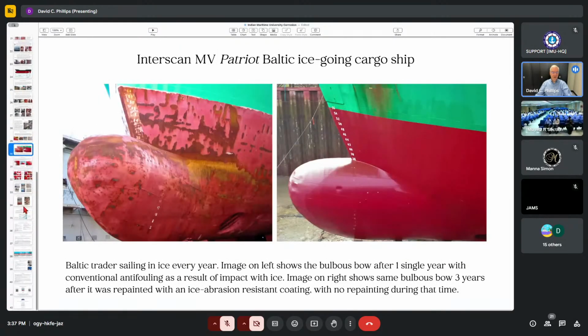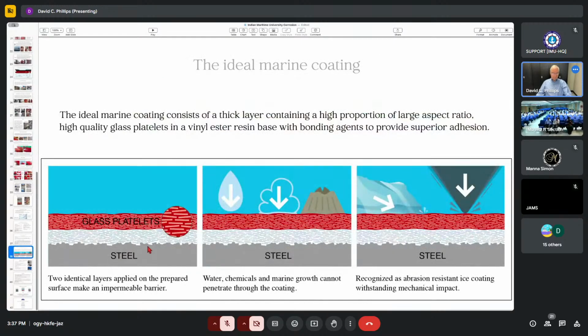Okay, so I'm going to tell you a little bit about this type of coating. Here you see two layers of the same material. They're different colors just to show you that it's applied in two different coats. That is 1,000 micron, 1 millimeter, 40 mil of coating applied to bare steel. It could also be aluminum or GRP, it doesn't matter. It's applied, there's no primer, there's no coating in between, there's no coating on top. It's just a millimeter thick vinyl ester with glass platelets in it. And there's about 300 glass platelets between the surface of the coating and the steel.